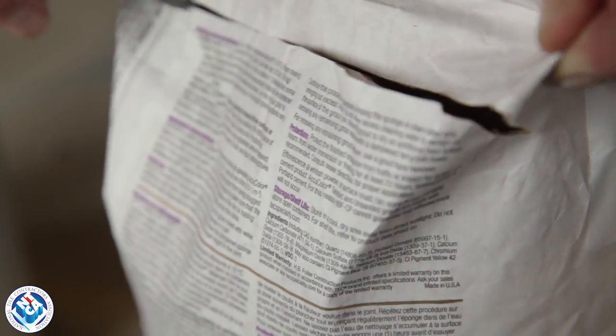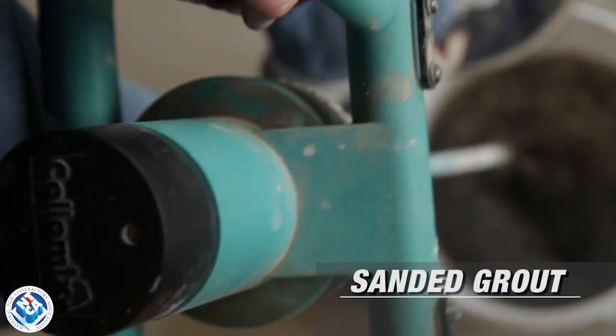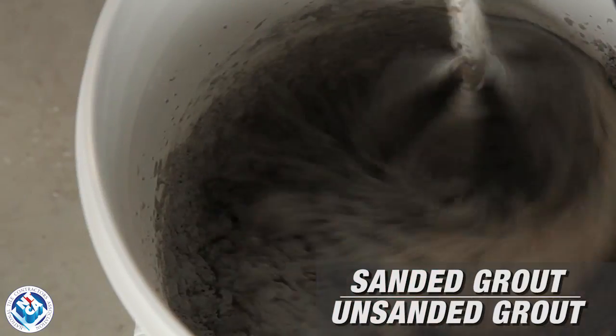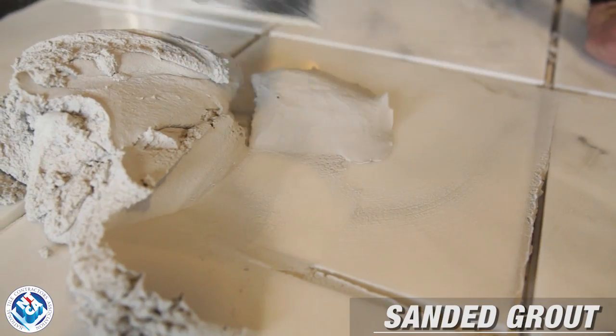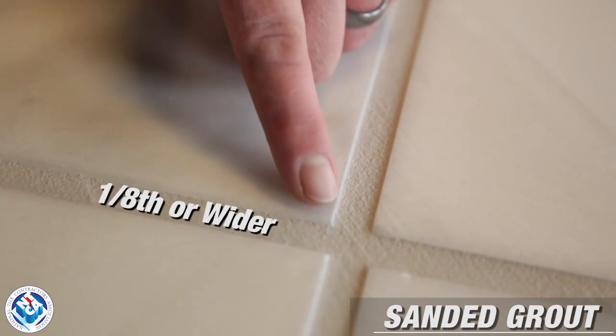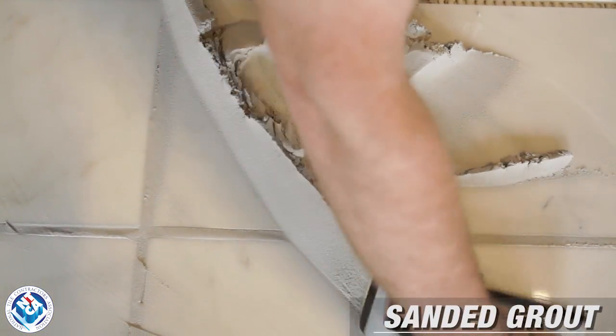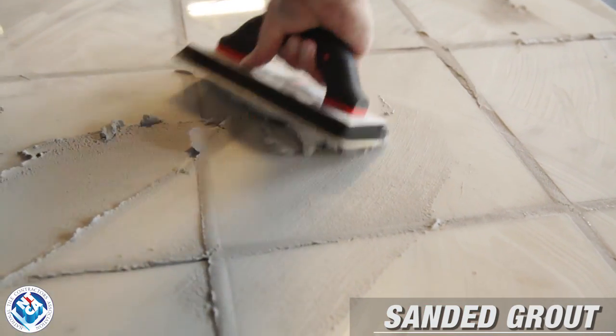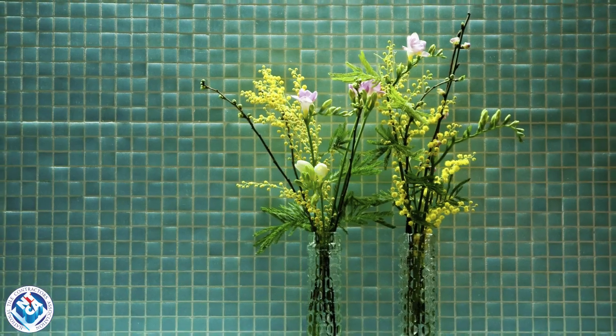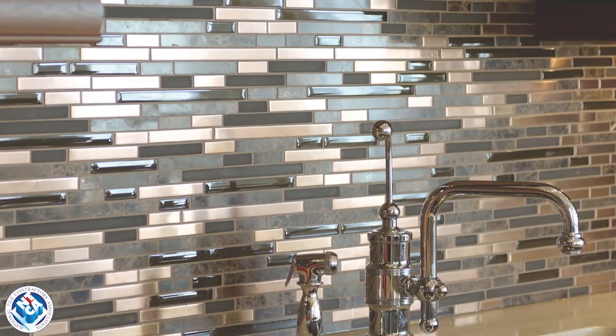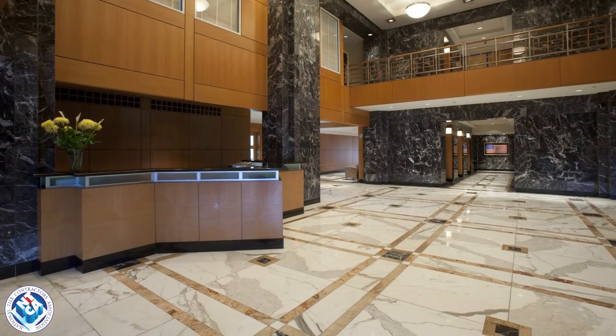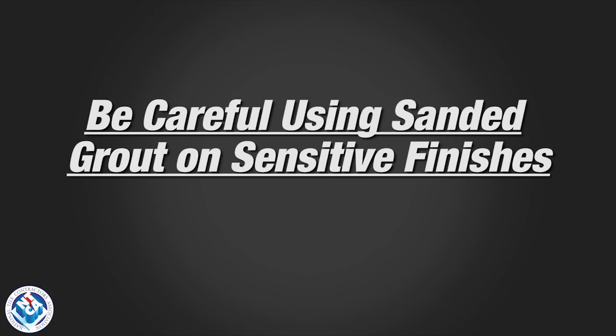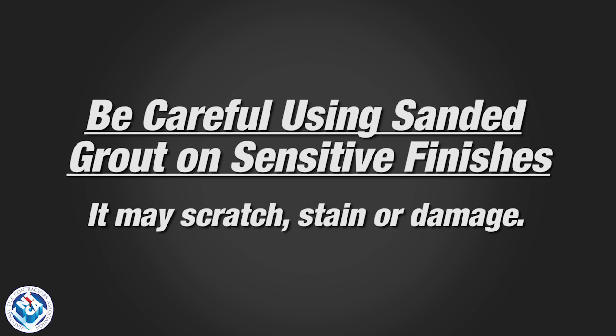The first one is cement grout. Keep in mind there are 2 kinds: sanded grout and unsanded grout. Let's start with sanded grout. This type of grout is used when joints are 1/8 inch or wider. Be careful using sanded grouts on sensitive finishes, such as glazed ceramic tiles, glass, metal, marble, polished stone, and agglomerate tiles. The reason? Sanded grout may scratch, stain, or damage these types of surfaces.